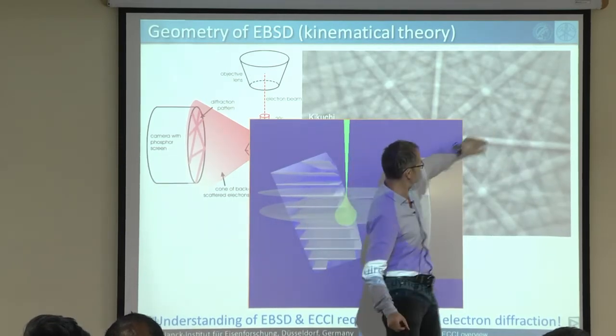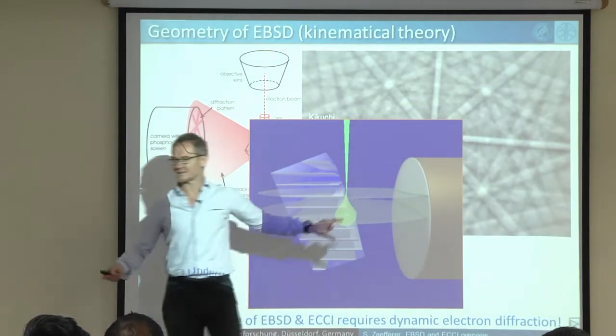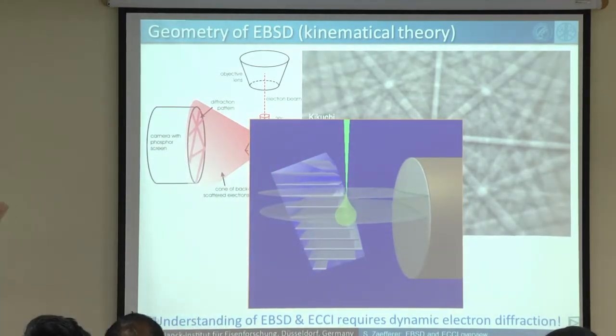And even in between the Kikuchi lines, it's even brighter. And this you cannot explain by the kinematical theory. It's impossible. There is no way to say from simple geometry why the intensity distribution is like that. Why are the Kikuchi lines black and the Kikuchi bands in between bright?